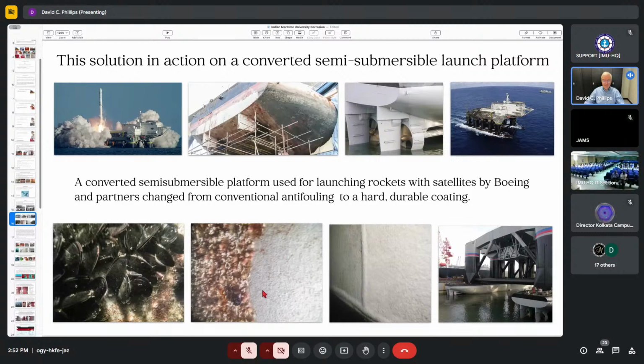And as you can see here, this is the same coating. This has been cleaned, it's 10 years on. It's been cleaned many times. The fouling has been removed, and it's very heavy fouling. And the coating is in its original condition, and they could sail again and get good fuel consumption. So this worked for them.